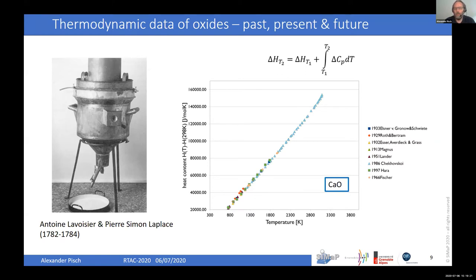If you want to go to higher temperature, you have to do it the other way around. You have to heat the sample up to a temperature from 1500 to 3000, and then you can drop it into a calorimeter at room temperature. The main difficulties here are the temperature measurements and the reaction of the sample with the crucibles or the vaporization effects. So again, the higher you go in temperature, the more difficult the measurement is.